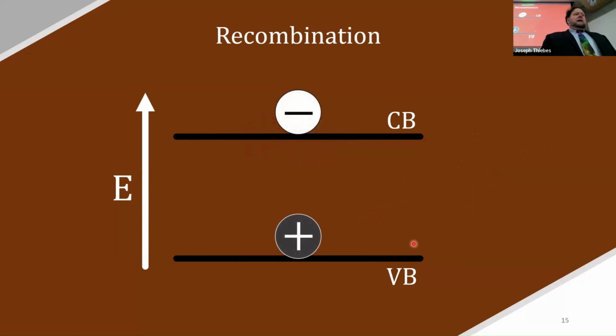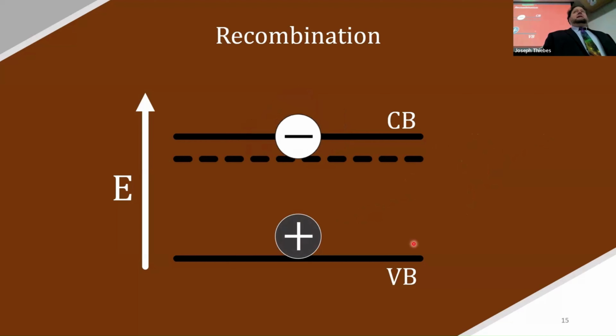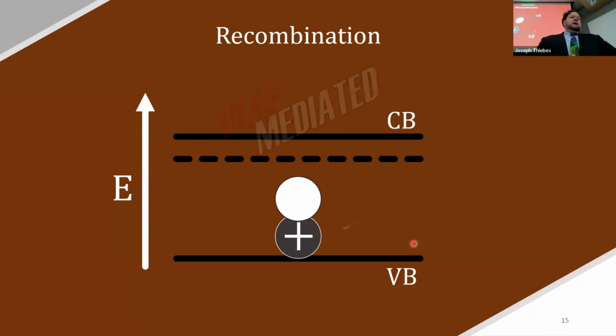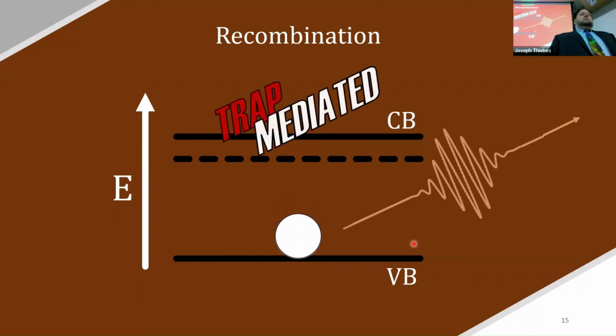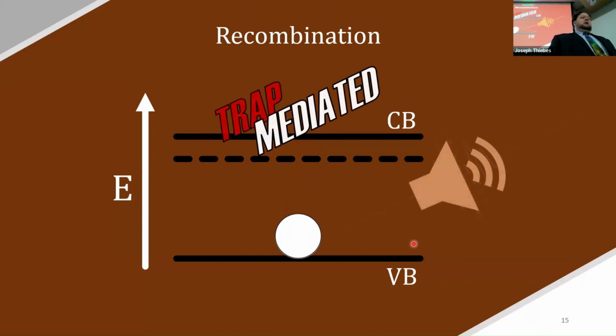You can also have the electron go into a trap state, which is a slightly lower energy. It's a lower energy that's within the band gap. And that's usually associated with a defect in the material or a surface, which is kind of a defect because the material ends. It can emit a photon from there, and that's called trap-mediated recombination. It can also put the energy into the lattice as heat.